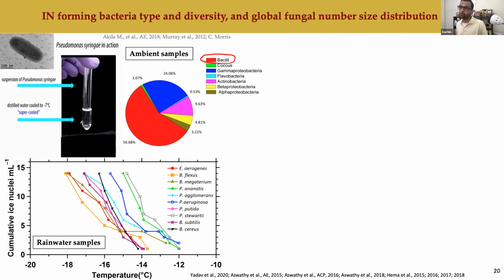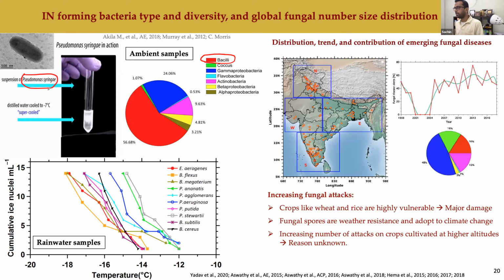Now look at this example. This is supercooled water at minus 7 degrees centigrade. But the moment you put this Pseudomonas syringae bacteria in that, the water immediately freezes. Whereas if you want to freeze that water by using some other non-bioaerosol, you need a temperature of around minus 30 to minus 40 degrees centigrade. This is how effective the ice nuclei are.